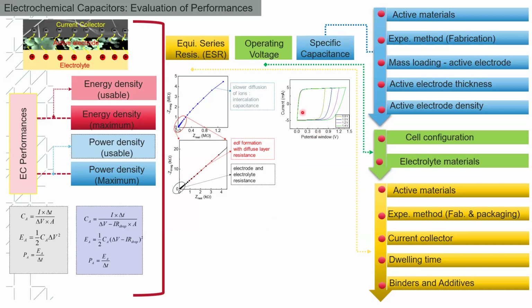Another one is the cyclic voltammetric analysis. For example, if you are using an electrochemical double layer based capacitor, this CV loop will be almost rectangular in shape. That means there is no redox reaction. But in some cases, we are using metal oxide, then a pseudo-rectangular shape is observed because of the redox reaction of the material. And depending on the operating voltage, you can change the CV analysis as well.